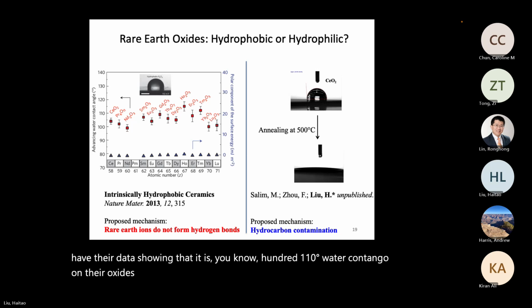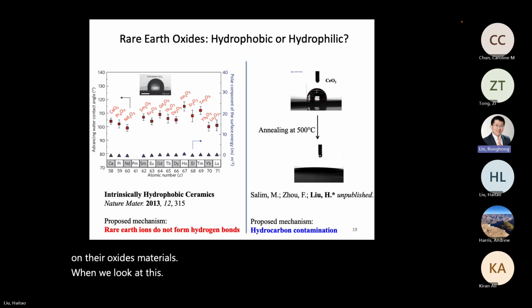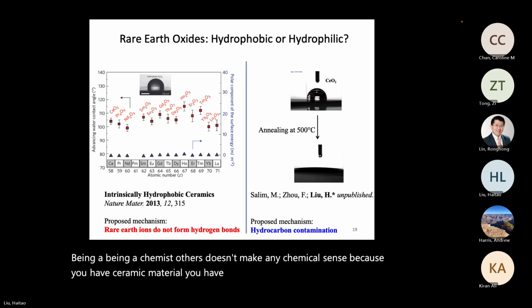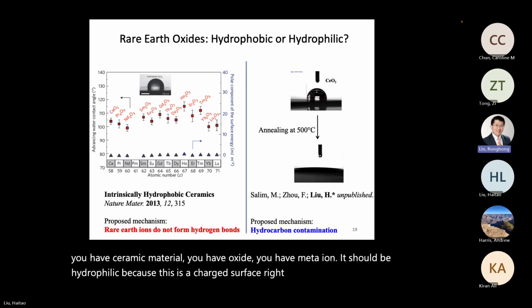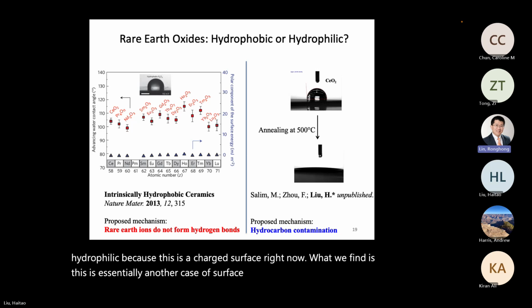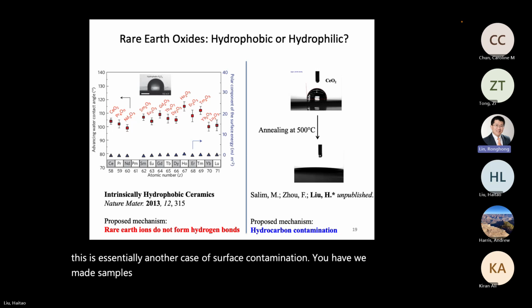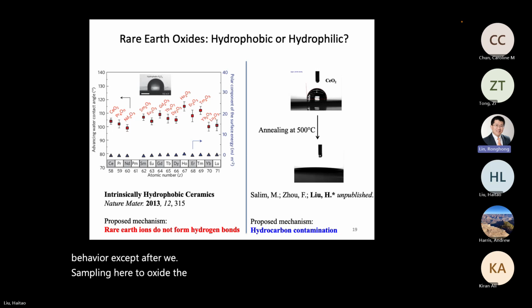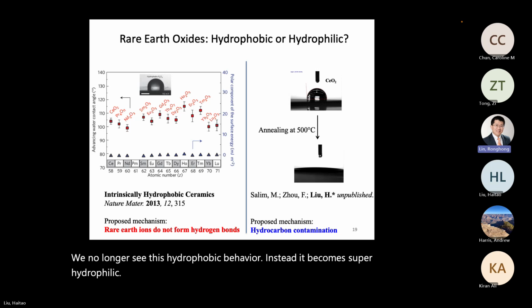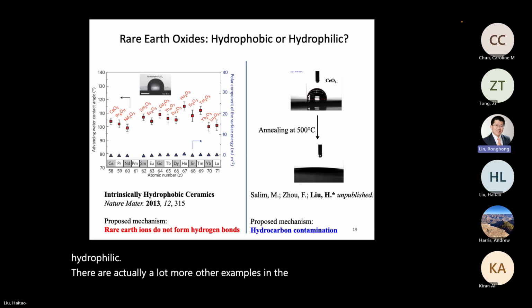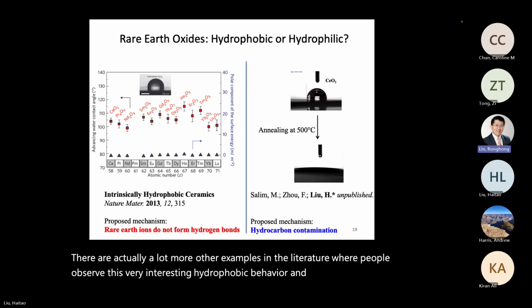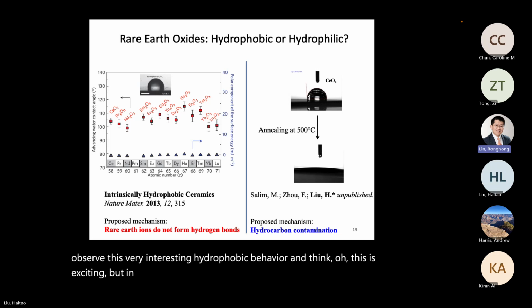oxide materials. But we look at this, being chemists, all this doesn't make any chemical sense because you have a ceramic material, you have oxide, you have metal ion. It should be hydrophilic because this is a charged surface. Right? Now, what we find is this is essentially another case of surface contamination. We made rare earth oxide samples, and we can reproduce their hydrophobic behavior, except after we heat the sample in air to oxidize the surface at high temperature, we no longer see this hydrophobic behavior. Instead, it becomes super hydrophilic. And there are actually a lot of other examples in the literature where people observe this very interesting hydrophobic behavior and think, oh, this is exciting. But in fact, it's simply because their lab air is dirty.